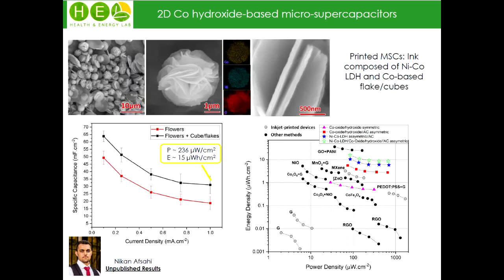In the next step, we used this composite ink to modify an LDH, nickel cobalt based LDH, and the capacitance was nearly 30% enhanced with addition of this ink to the LDH system.